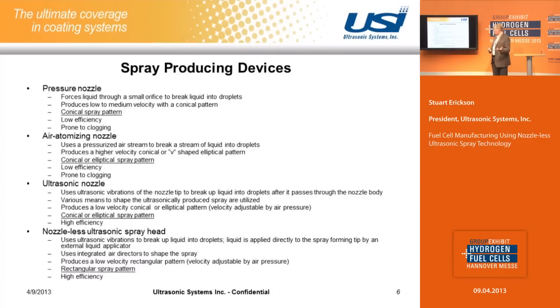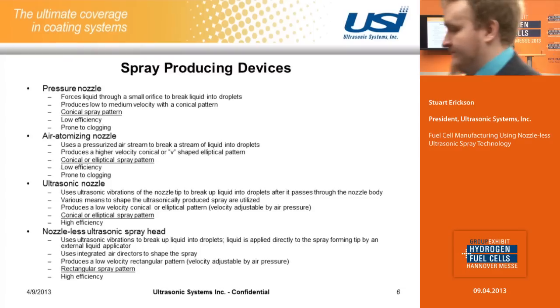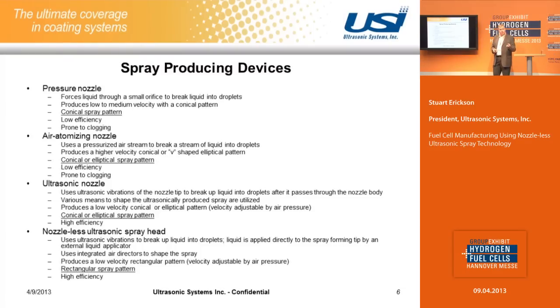Then there's ultrasonic nozzle technology, which uses ultrasonic vibrations to create the spray, and it uses low pressure air to shape the spray. This technology also produces a conical or an elliptical pattern depending upon the spray shaping that's used. But this is a very high efficiency technology, so anywhere from 90 to 99% of what is sprayed with the ultrasonic nozzle will reach the substrate.